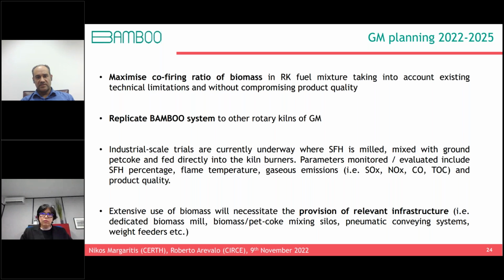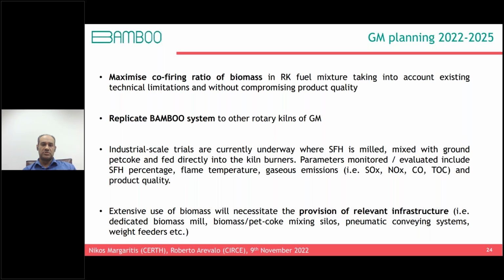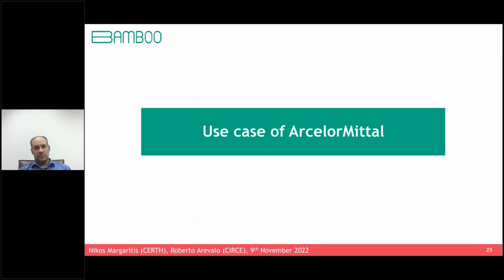The planning of GM is to maximize the co-firing ratio to above 50%, taking into account the existing technical limitations and without compromising product quality, as I said in the beginning. GM has 3 rotary kilns. This was applied in rotary kiln 3, so this can be replicated also to the other 2 rotary kilns of GM. But important is that the extensive use of biomass means that you have to invest in relevant infrastructure: dedicated biomass mills and biomass-petcoke mixing silos, in order to better handle the biomass-petcoke mixture. So an investment has to go there in order to handle the new fuel that you are going to use in your production process.